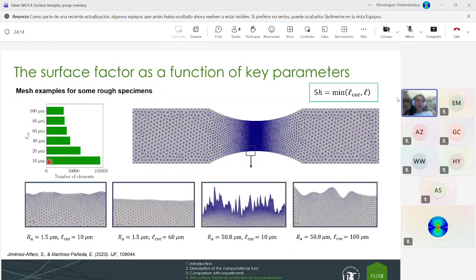So each time we are changing a parameter in our tool, what we are doing in the end is changing the rough profile. It means that we are changing the mesh. So here you have some examples. For example, this critical case where we have a very big value of the average surface roughness and a very low value of the correlation length. You can see the extreme peaks.